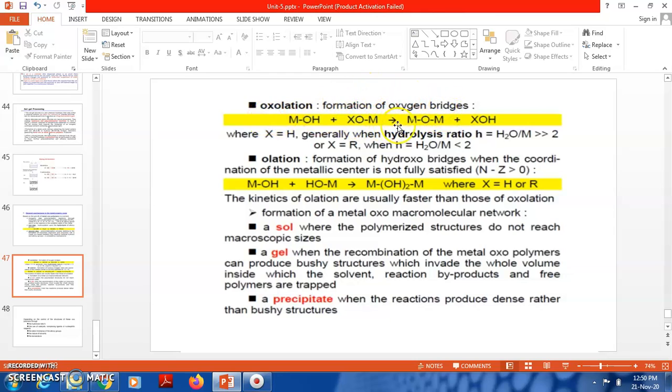Oxolation is the formation of oxygen bridges. Generally when the hydrolysis ratio H₂O/metal is high, they will develop thin sols. Olation is the formation of hydroxo bridges when the coordination of the metallic center is not fully satisfied. The kinetic of olation is usually faster than oxolation. When polymerized structures do not reach macroscopic size, that is a sol.